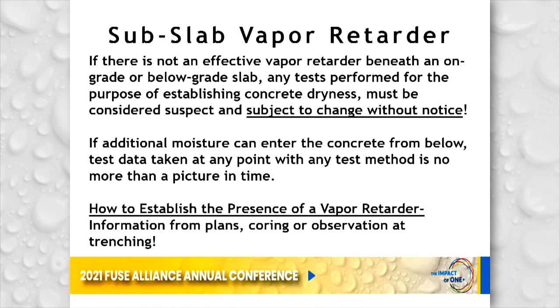So again, we want to talk about that subslab vapor retarder. And it must be known, must be understood, that if there's not an effective vapor retarder beneath an on-grade or below-grade slab, any test performed for the purpose of establishing concrete dryness must be considered suspect and subject to change without notice. If additional moisture can enter the concrete from below, test data taken at any point with any test is no more than a picture in time.